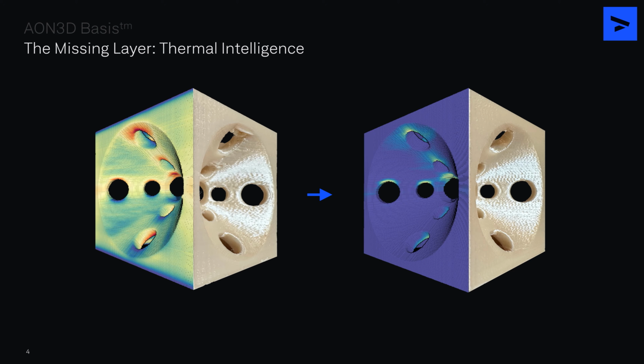When you see that kind of drooping or sagging, it's not necessarily because of the overhang angle, but rather because that polymer had no mass around it in which to distribute heat. Without Basis, your part would have been manually optimized within your slicer layer by layer. Instead, what you're getting is a dynamic, transient, centimeter by centimeter optimization where you are controlling the print speed, the flow rate, everything in conjunction to get you a good looking and thermomechanically optimized part, which you see on the right.